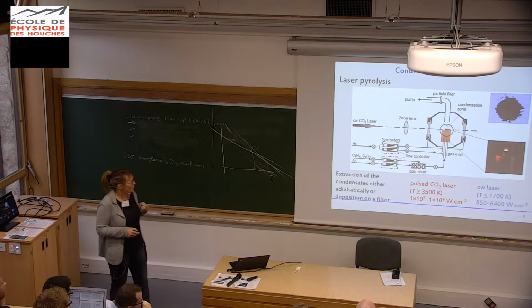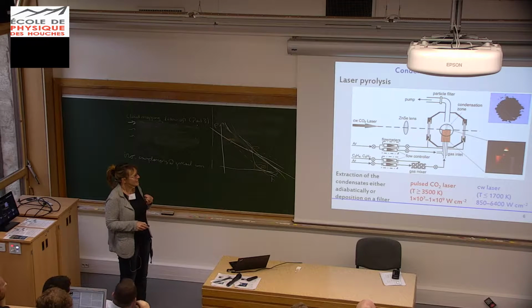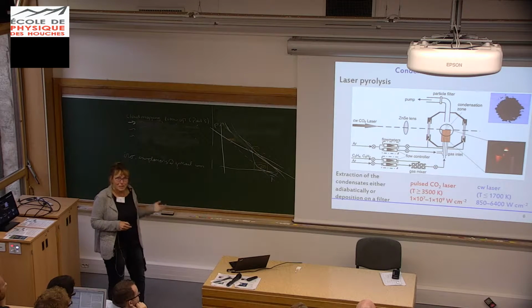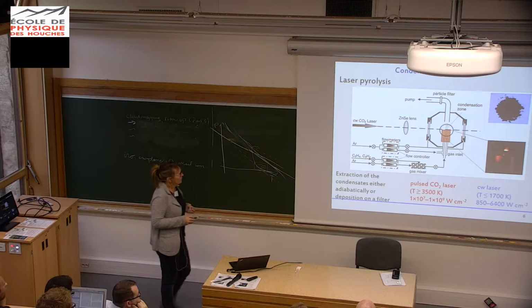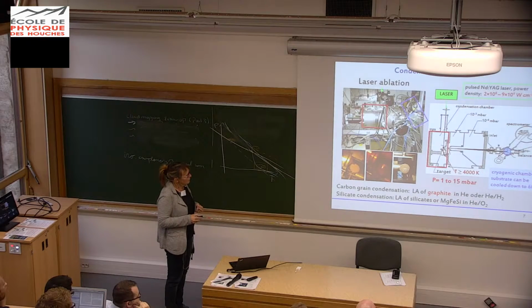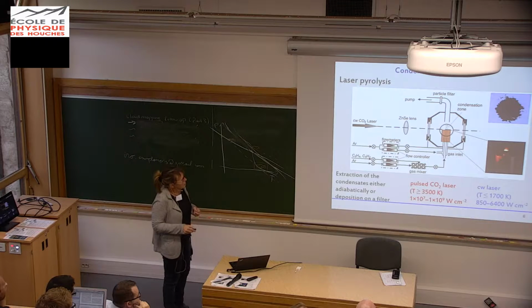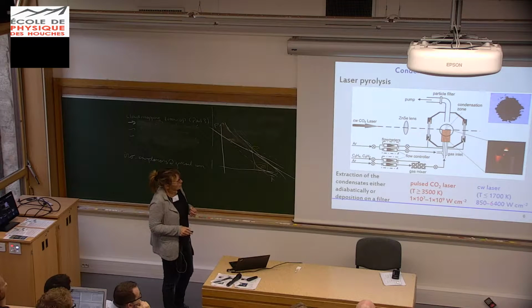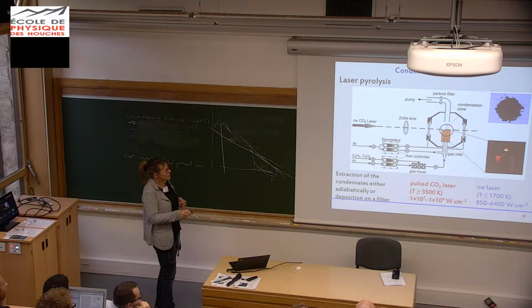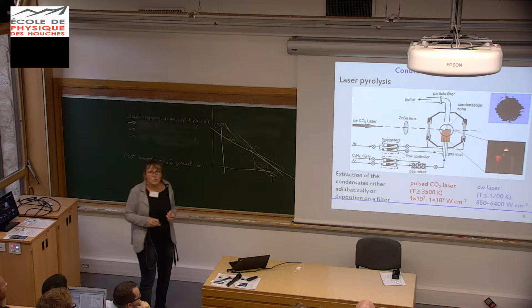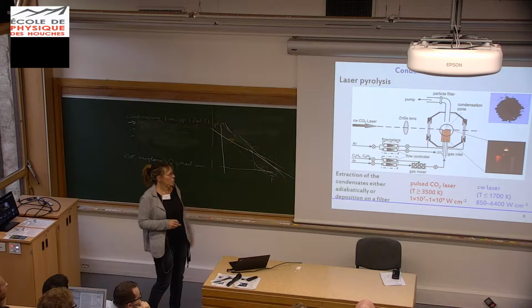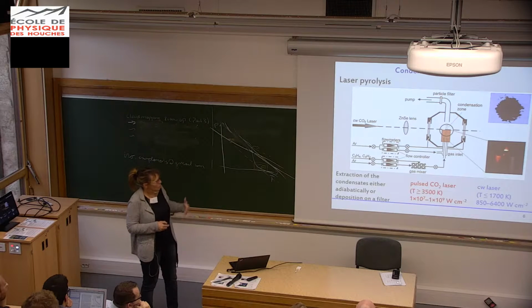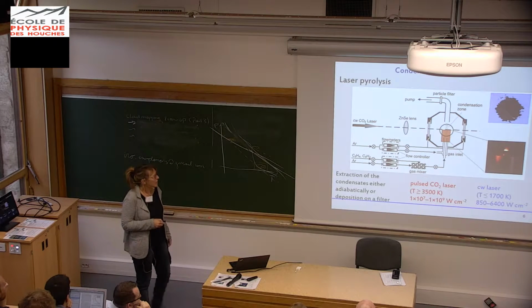This is the vibrational temperature of a gas molecule. If we use a continuously working laser, the power density is much lower, and we reach only temperatures lower than 1700 K, so up to 800 or even less.